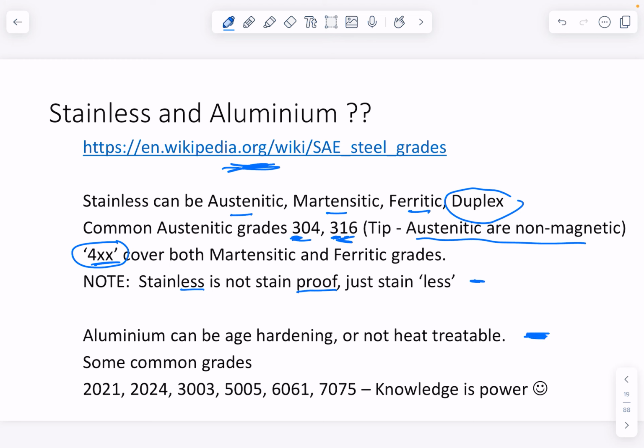Aluminium, just as complicated, if not more. There's age hardening, and there's not age hardening, or not heat treatable. If you're going into your kitchen and you open a bit of aluminium foil, it's going to be an 1100 grade, which has a yield strength of about 60 MPa or something silly like that. 2011, 2024 are commonly round bars. These guys tend to be in sheet form, although this can also be done as a round bar. 7075 is so-called aerospace grade. But all of these will have different ways in which you can weld them. One of the difficulties with welding aluminium is the oxide layer melts at a higher temperature than the substrate.